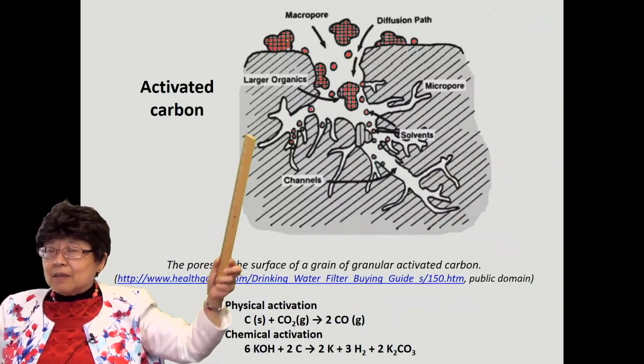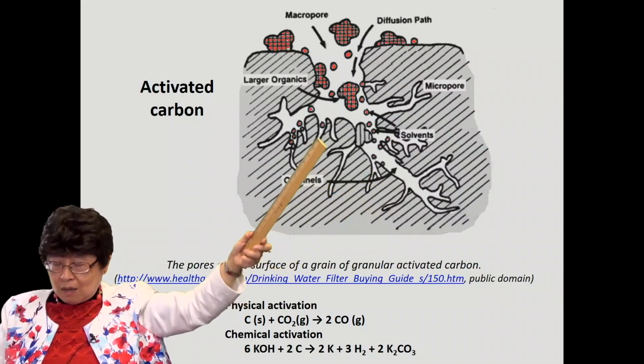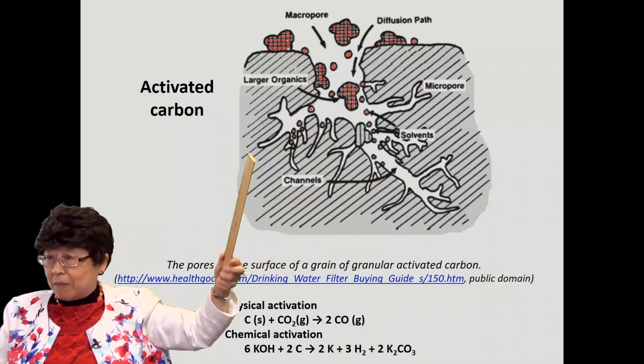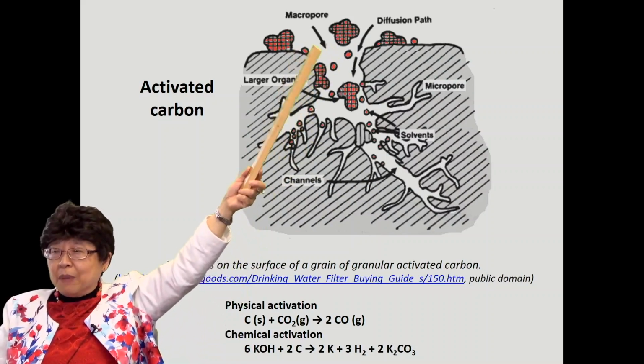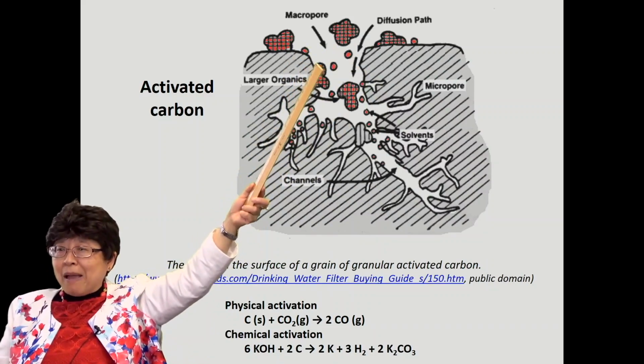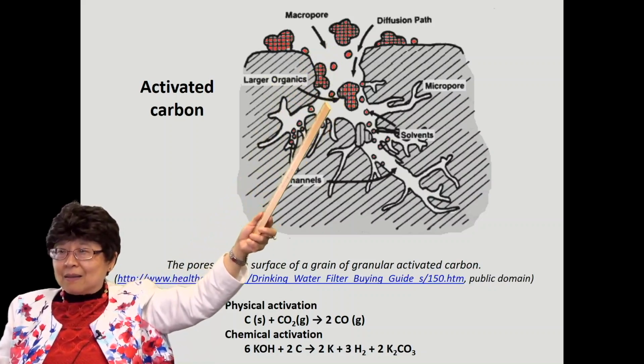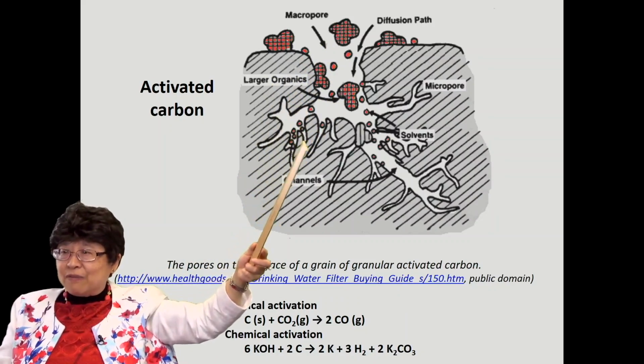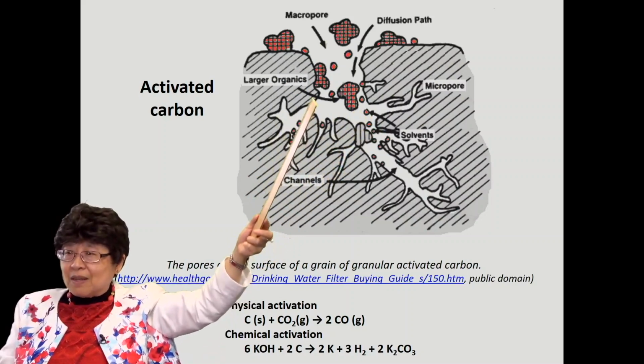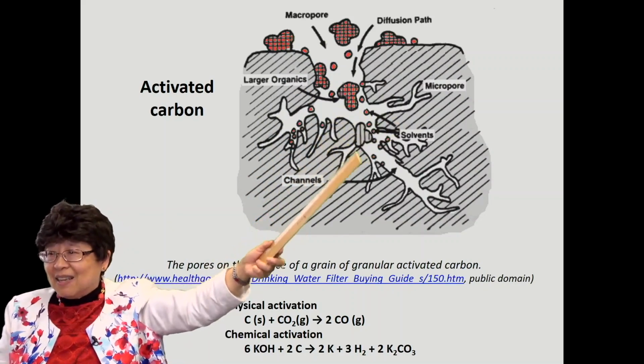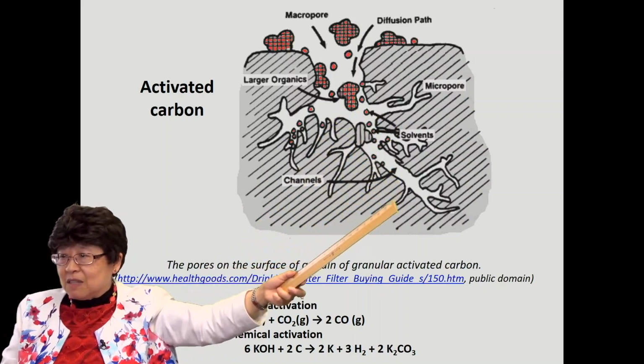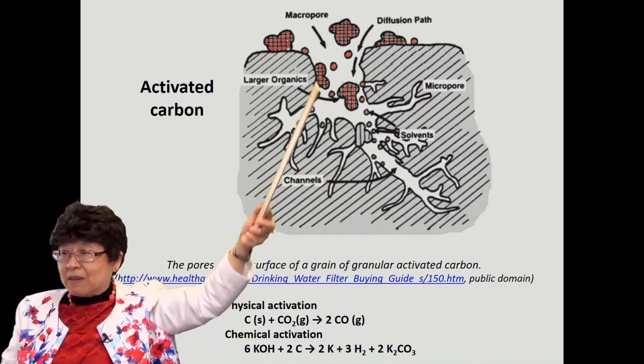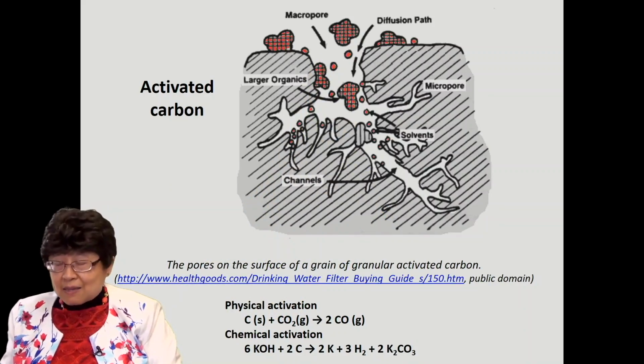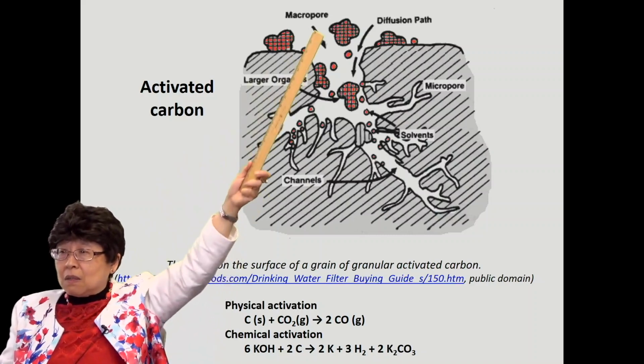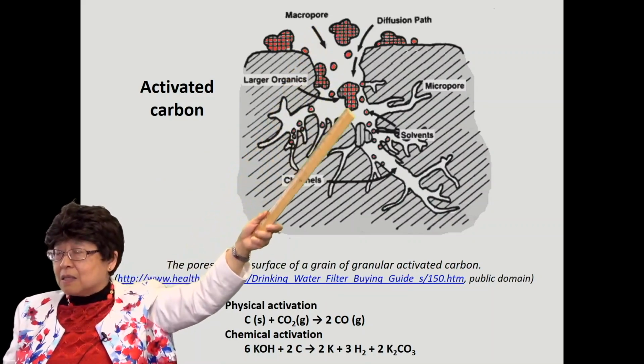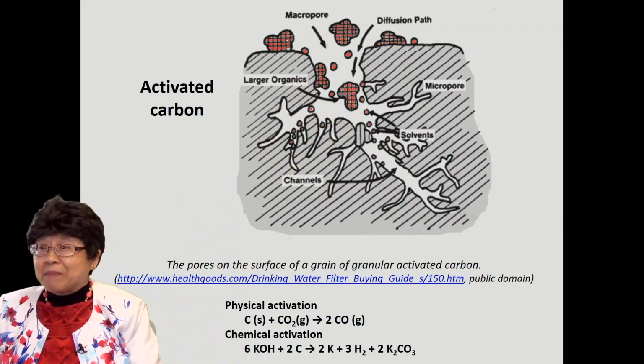And this is a typical configuration of the activated carbon, the holes. You have a big mouth called macropore, and then the oxidation digs in, and you have smaller pores, like tunnels, digging in, and you have the tips of these are very, very tiny, but the mouth is much bigger. So you have a gradation of various sizes of pores. But this is all accessible from the outside. This is the surface pore, but it digs in.